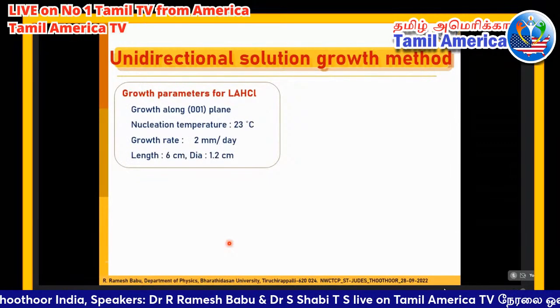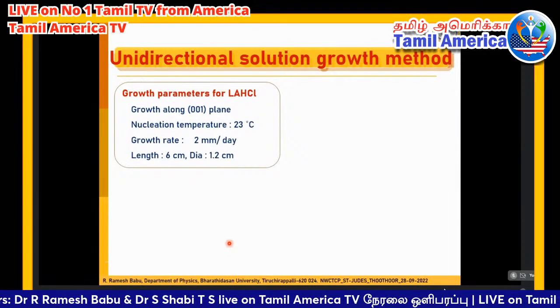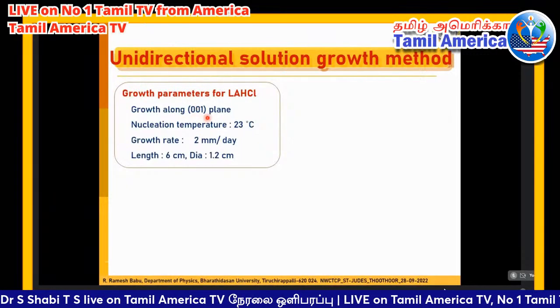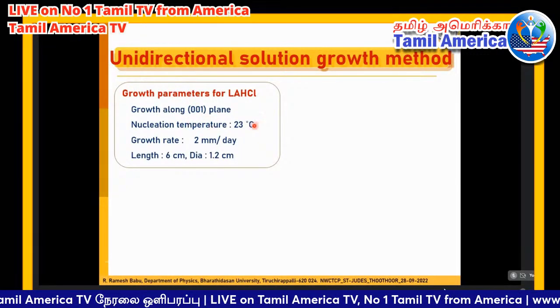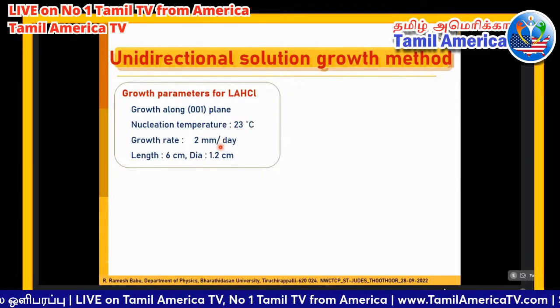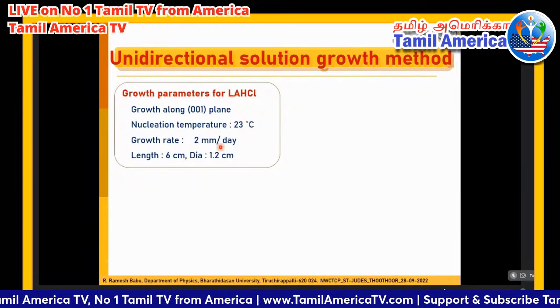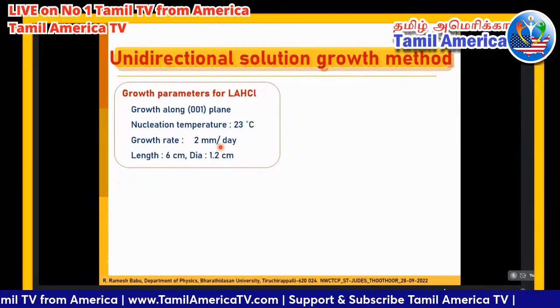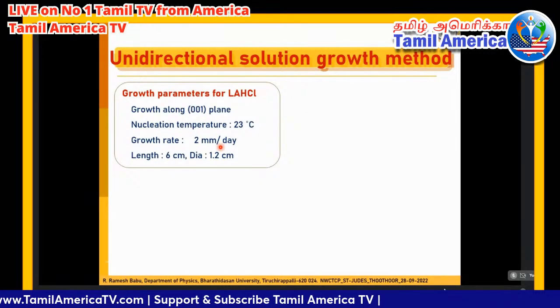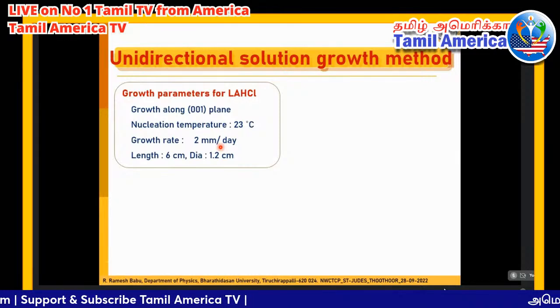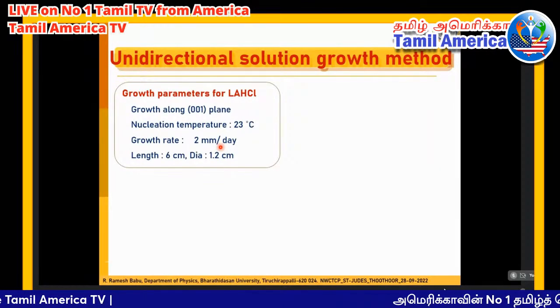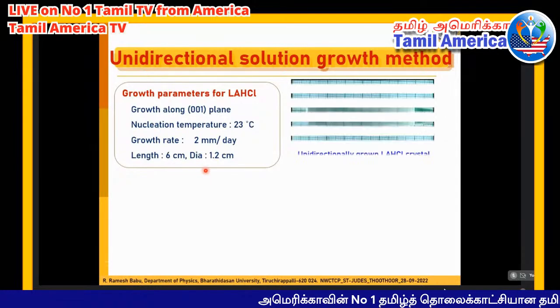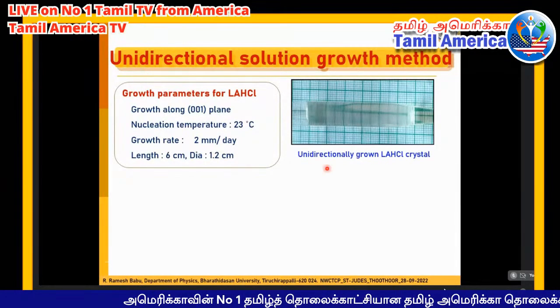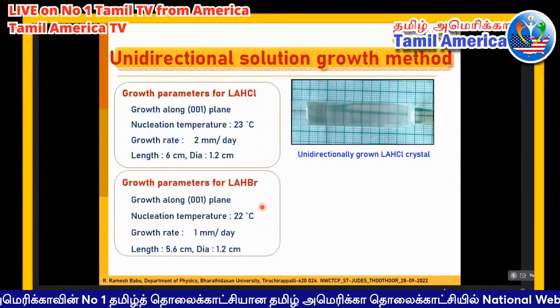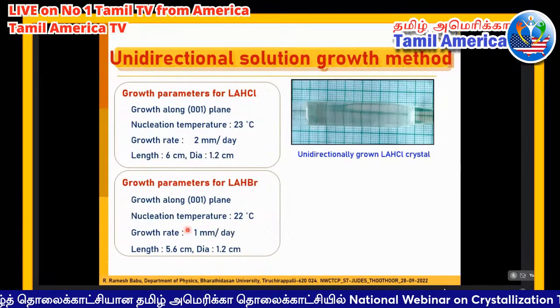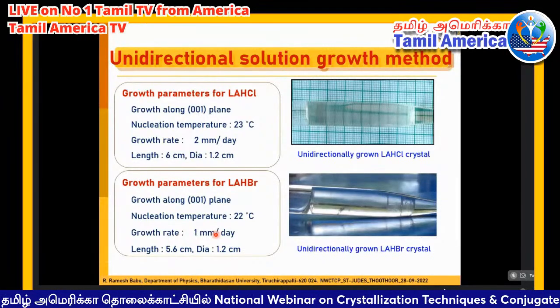by the unidirectional method. In this unidirectional method, we can choose the proper direction, the 001 direction, and the nucleation temperature is 23 degrees centigrade. The growth rate we can measure using this technique is 2 mm per day. We can also increase the growth rate, but we need to optimize it by trial and error. So this is the dimension of the grown single crystals. This is the unidirectionally grown single crystal of LaHBr, at 1 mm per day growth rate. This is the grown single crystal of LaHBr.